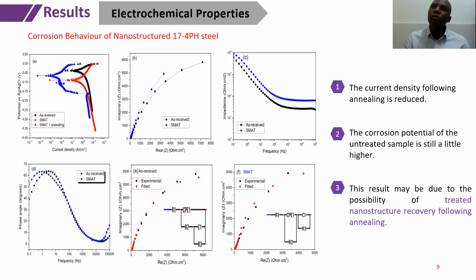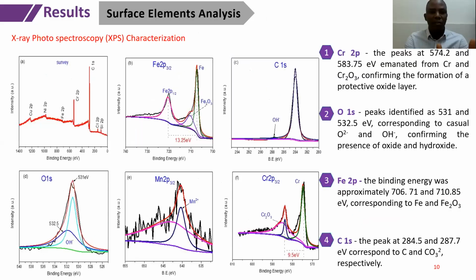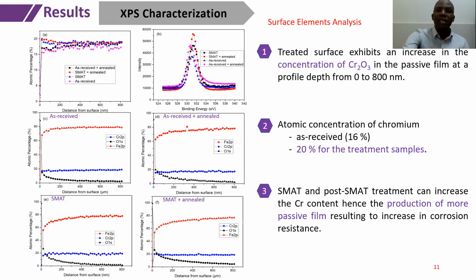We went ahead to do the surface element analysis to see if we can actually characterize this material. And our method shows that all the elements that are in this sample contribute to the corrosion properties. Also, I can see here, the amount of chromium in a sample plays an important role in corrosion properties. We notice that our sample that is treated with SMAT+annealing has the highest level of chromium, which shows that it has the best corrosion properties.